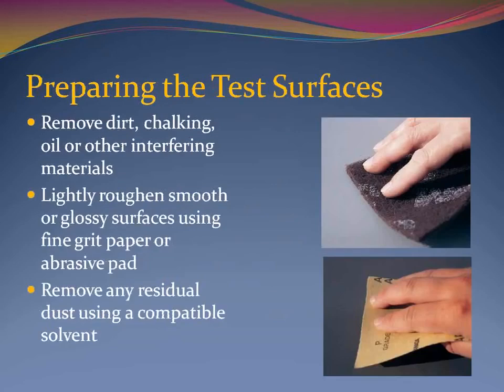Once a test area is selected, you may need to prepare the surface prior to attaching the loading fixtures. Ensure the area selected is free of grease, oil, dirt, chalking, water, protrusions, or other conditions that will interfere with attachment. The area must also be flat and rigid and be large enough to accommodate the test apparatus as well as triplicate loading fixtures. According to the standard, a substrate thickness of less than one-eighth inch usually causes a reduction in adhesion compared to a one-quarter inch substrate thickness, so rigidity of the substrate is an important consideration.